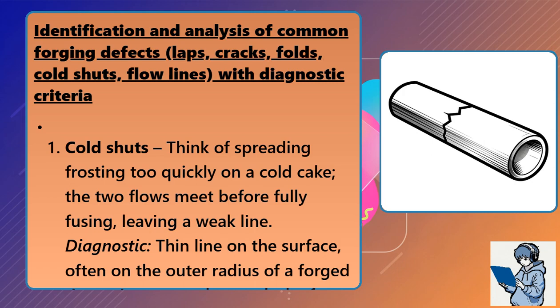Cold shuts: think of spreading frosting too quickly on a cold cake. The two flows meet before fully fusing, leaving a weak line. Diagnostic: a thin line on the surface, often on the outer radius of a forged ring; microscopy shows a lack of grain bonding.